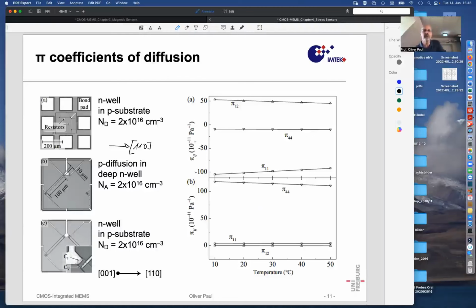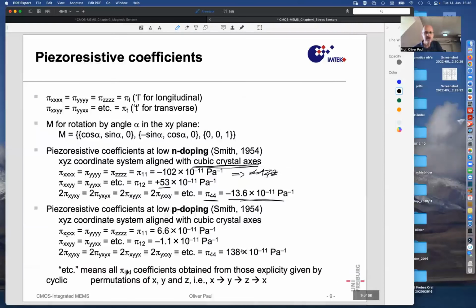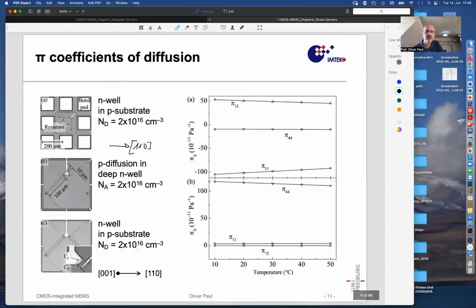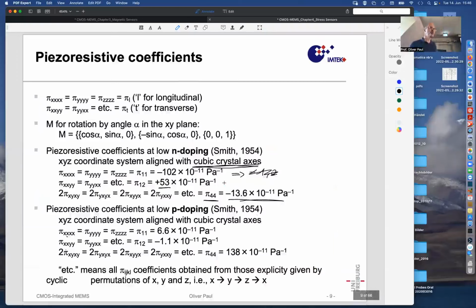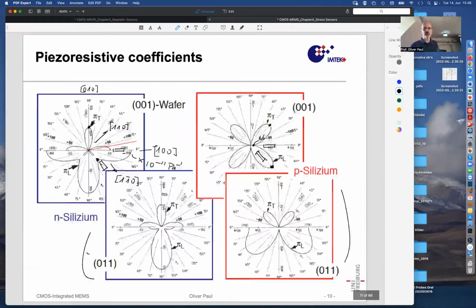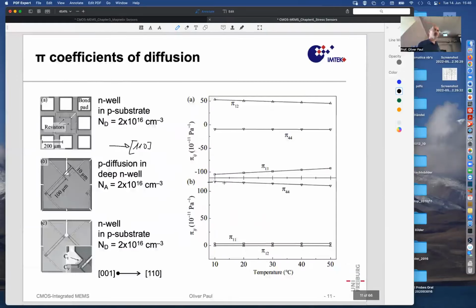And you see here some values tabulated as a function of temperature, measured by Pascal Gischke, PhD student of mine, on these substrates. And the values correspond pretty much to what one expects. So 102. Here something like minus 13. Here something around 53, and then they all decrease with temperature. This value here is maybe smaller than 136. This P doped should be 138 for pi4. It's definitely not that value. But the coefficients that were mentioned here are actually for low doped P silicon, and this material may not be so low doped. It is also known that the doping level decreases the piezoresistance coefficient, making the piezoresistor flat again.